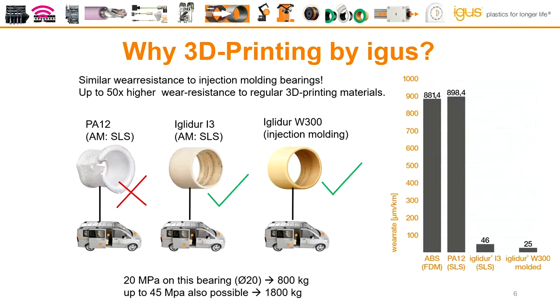So if I put it more in numbers, this is the test. As I'm saying, it's a 20 millimeter bearing pressed in a housing, and there's a shaft running in it. And I can put a load on it up to 1,800 kilograms. So it's more like a bigger car. You can put that as load on such a 20 millimeter bearing, and you still have a similar wear rate compared to injection molded bearings. You see, iglidur W300 is an injection molding material and has a wear rate of 25. The lower is better here. And iglidur i3 is with 46 very close to the injection molded bearing.